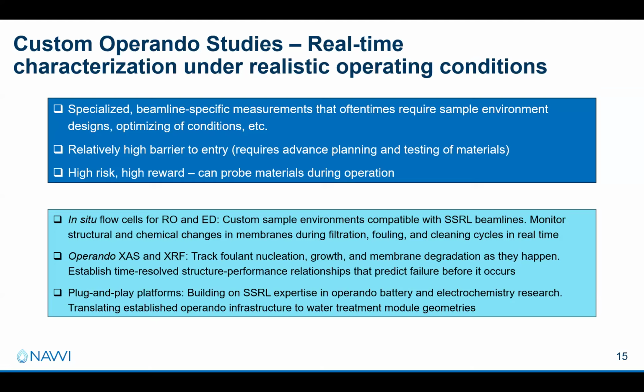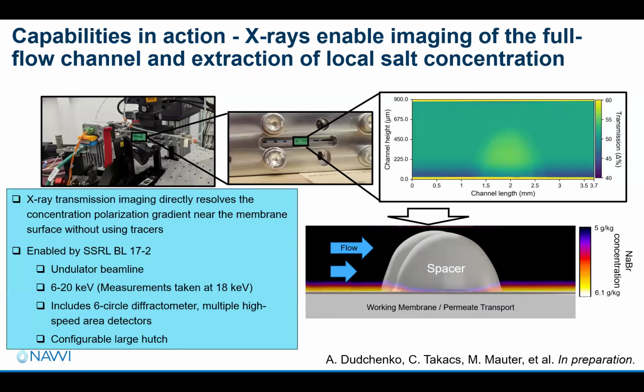And so what you can, for example, do is look at in situ flow cells for RO or electrodialysis or operando XAS. And so one example there is these experiments that were conducted at beamline 17.2. So that's one of our new beamlines. It's an undulator beamline that can run over quite an energy range from 6 to 20 keV. So you can look at a lot of different materials. We have a 6-circle diffractometer and multiple high-speed area detectors.